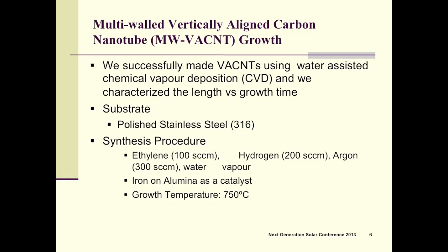In our lab, we successfully made vertically aligned carbon nanotubes on different substrates using different chemical vapor deposition methods. Initially, we used FTO as a substrate to grow carbon nanotubes, but after exposure to the growth conditions, the FTO is destroyed. So we shifted to other substrates.